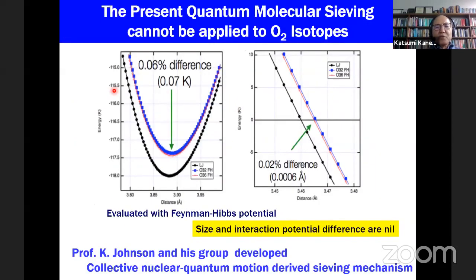At first we wondered whether the quantum molecular sieving can be applicable to oxygen isotopes. Using the quantum Feynman-Hibbs potential, we estimated the fluctuation difference. Such a difference is very, very tiny, 0.02% difference, and the interaction potential difference, 0.07 Kelvins, is negligible. So it is very difficult. But I'm sticky, so I like this theory, but I'm not a theoretician, so we should challenge. Anyway, we should challenge. Then we measured the oxygen isotope adsorption.